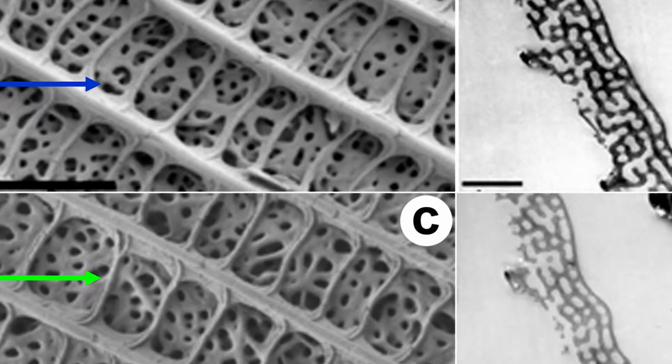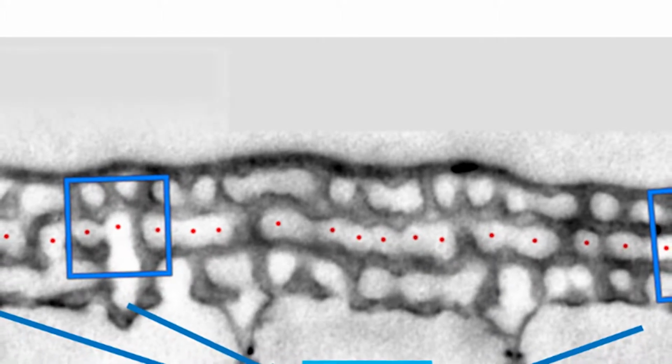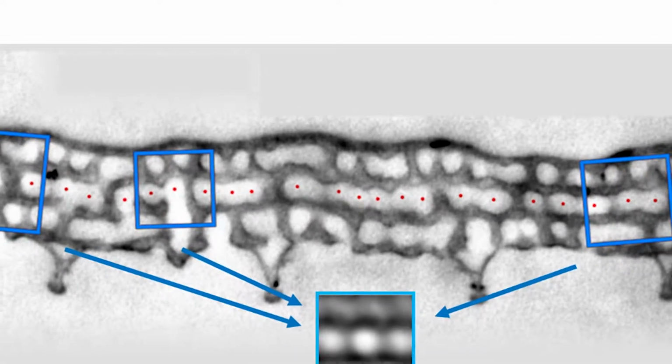It is not easy to reveal the three-dimensional structure of a butterfly wing scale because of its tiny dimensions. One has to carry out a careful correlated examination of the scanning and transmission electron microscopy images for that. Indeed, the biological photonic nanoarchitectures are not as regular as crystals in solid-state physics or artificial photonic crystals made by three-dimensional lithography. They always contain some randomness. In order to tackle this problem and reveal the order in the disordered structure, we developed a statistical procedure called direct space averaging.